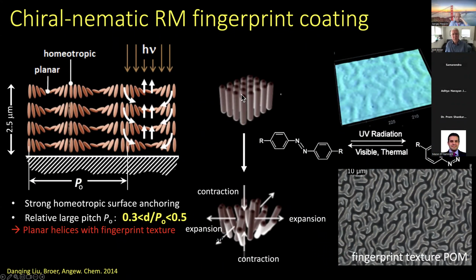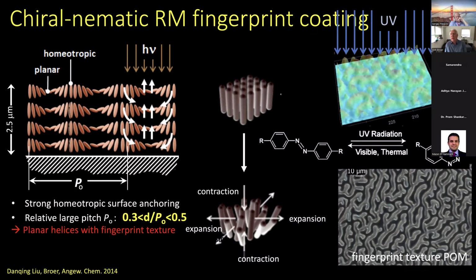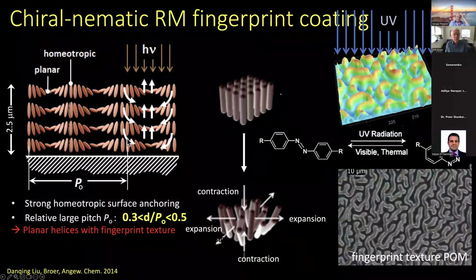Just because of the same reasons as they had the anisotropic thermal expansion again. Moreover, where the azobenzenes are oriented planar, they absorb also somewhat more light than when they are oriented perpendicular. And the overall result is that we go from close to a flat state, you see a little bit of surface structure because of the so-called Marangoni effect, to a much more corrugated state. So all the planar areas come up and the homeotropic areas go